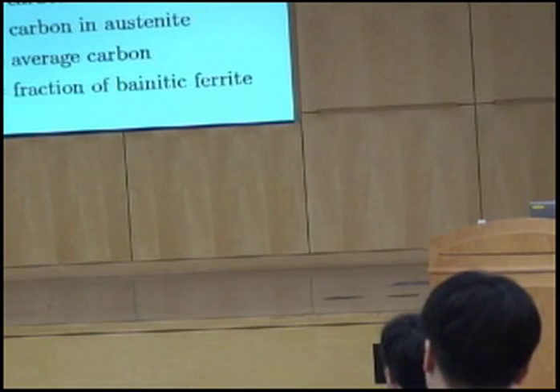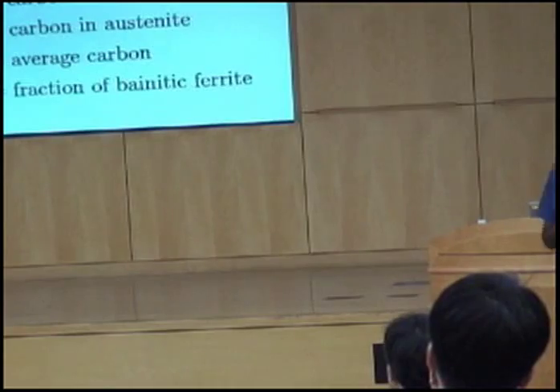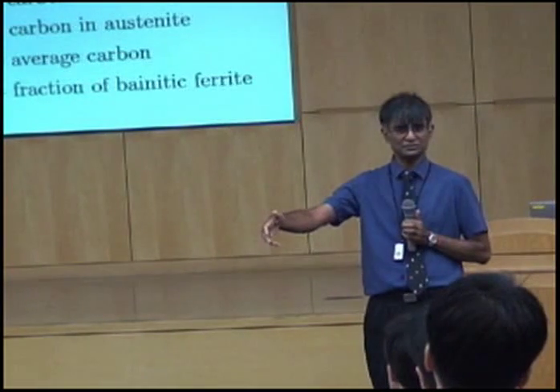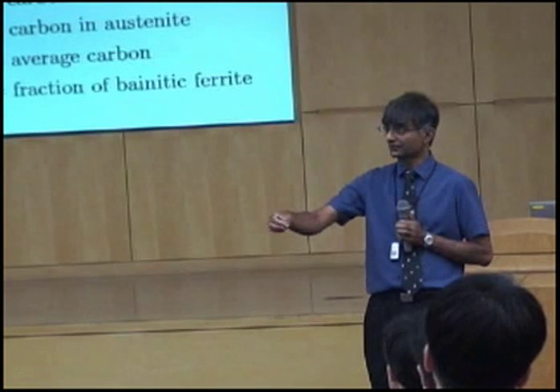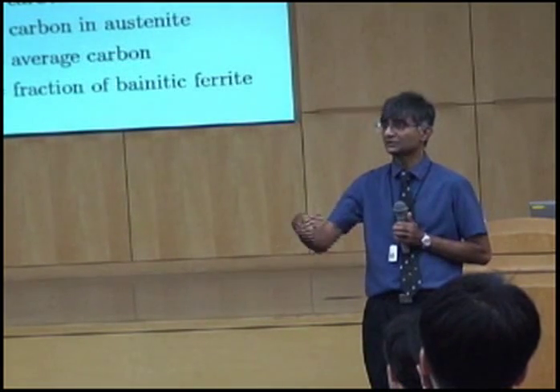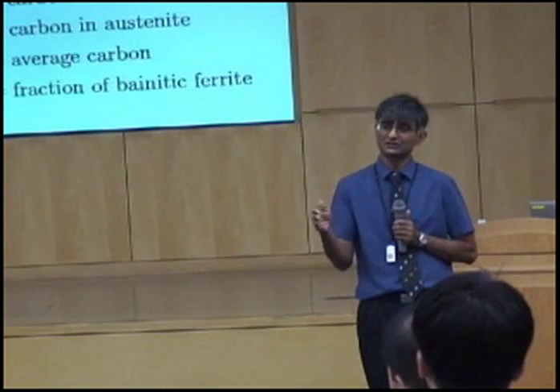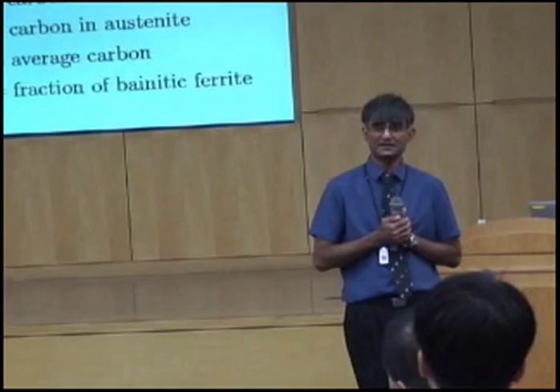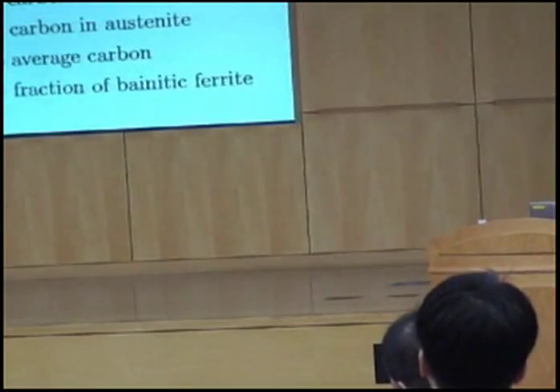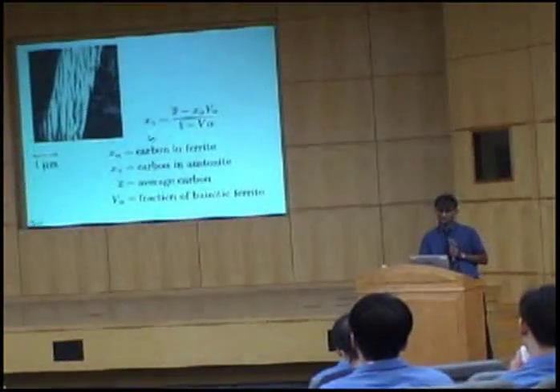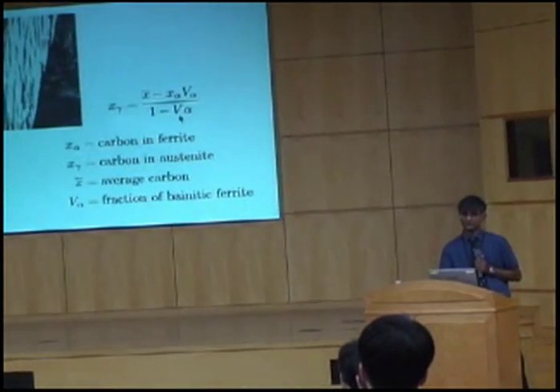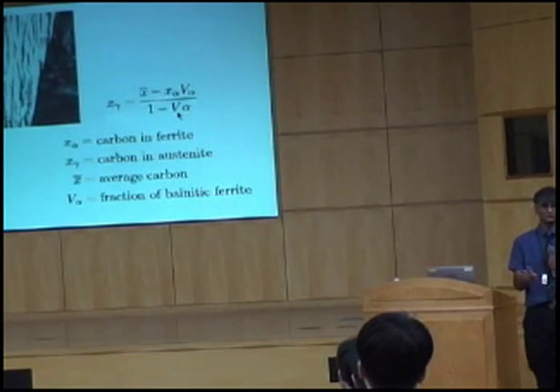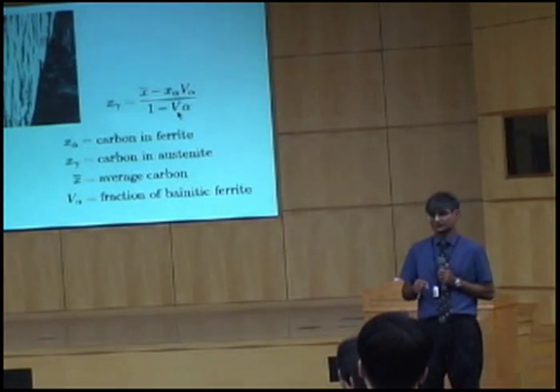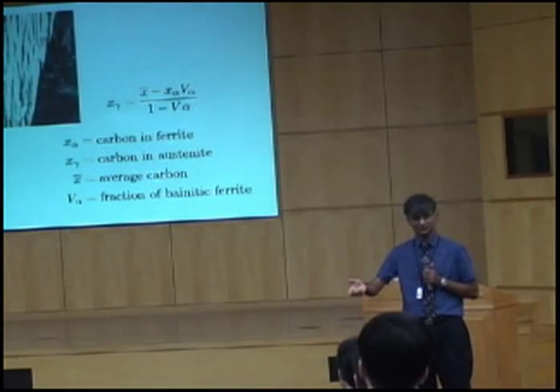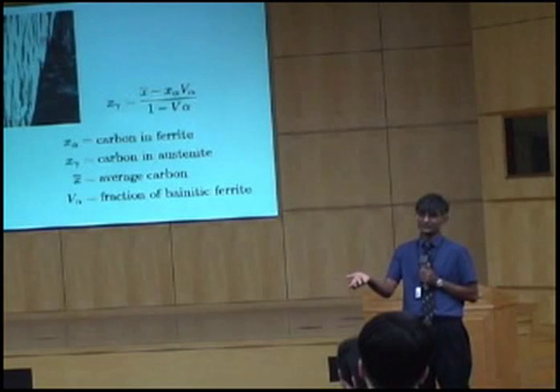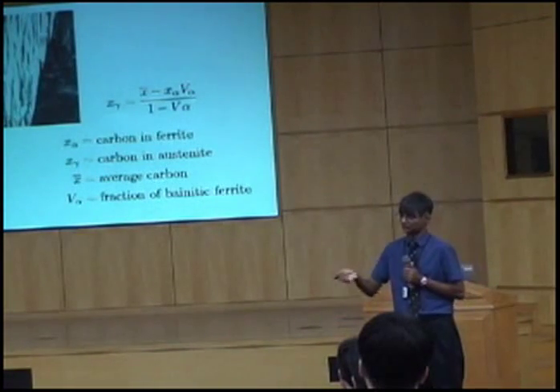Well, the first effect is that as soon as you introduce some bainite into the microstructure, the composition of the remaining austenite changes. Okay? And therefore, the strength of the martensite that you form from that austenite will be different. You can no longer assume that the composition of the austenite is the same as the average composition of your steel. So if you work out the carbon concentration in the austenite as a function of the volume fraction of bainitic ferrite, that is the carbon concentration which you must use to calculate the strength of martensite. So the bainite forms, it partitions carbon, and therefore the strength of the martensite actually increases. Okay? And we must take that into account.